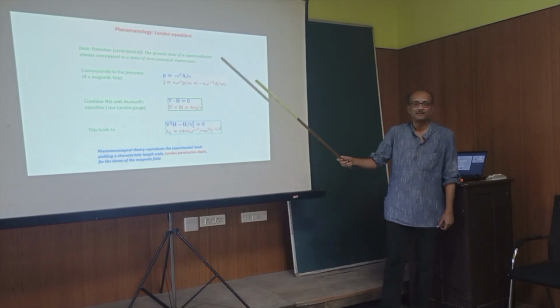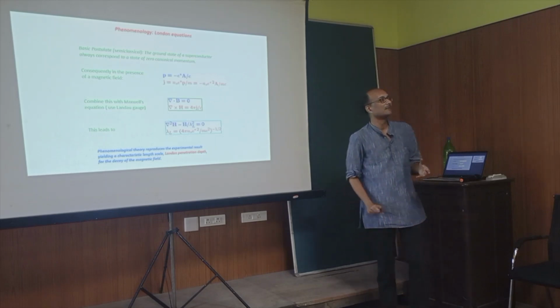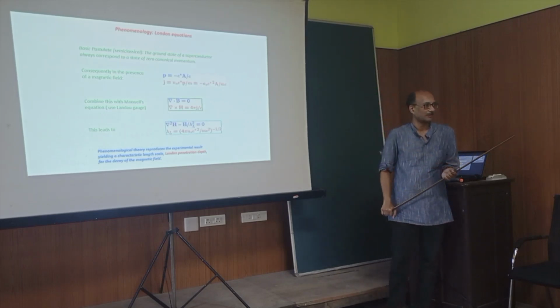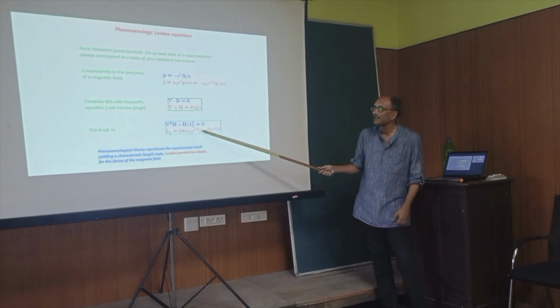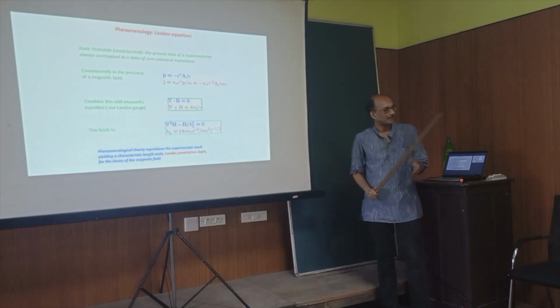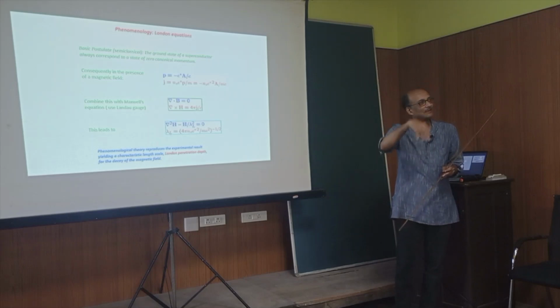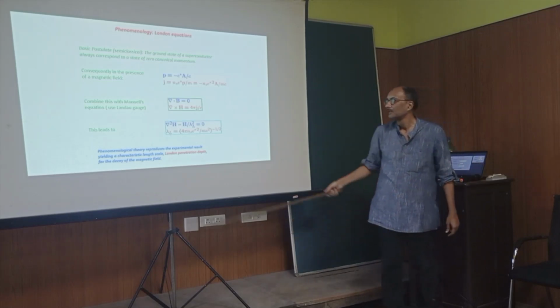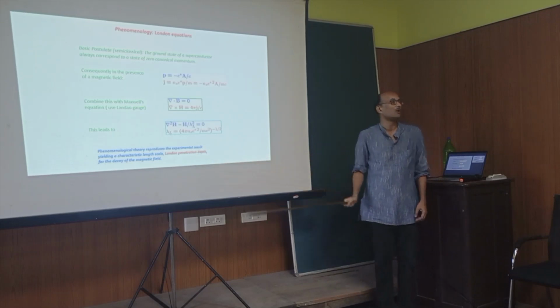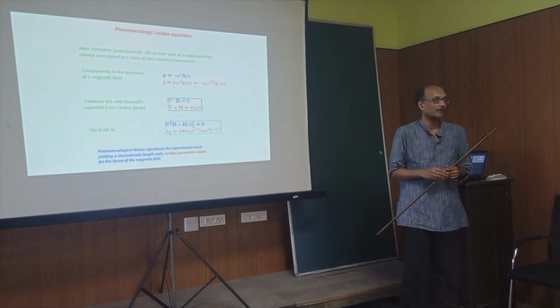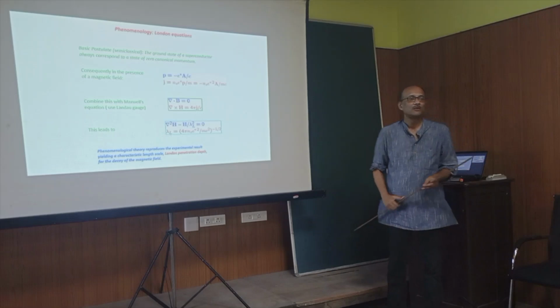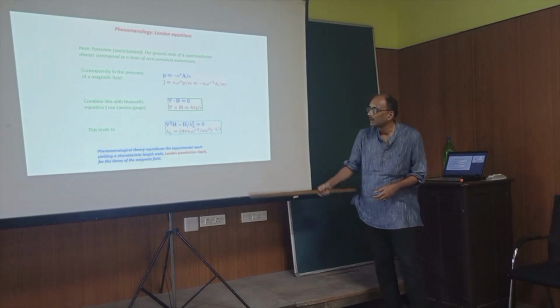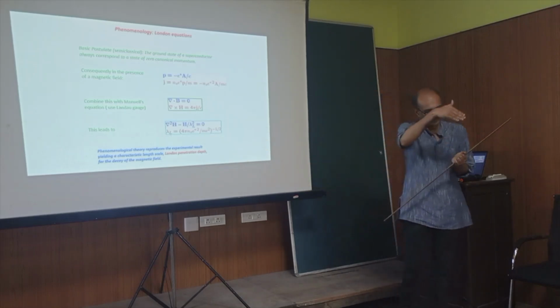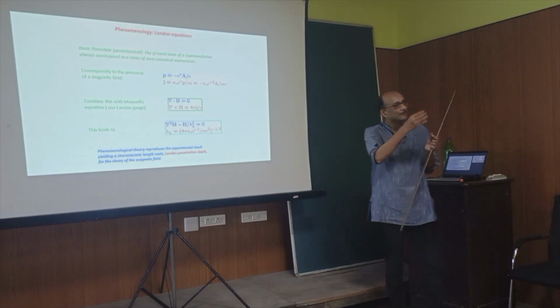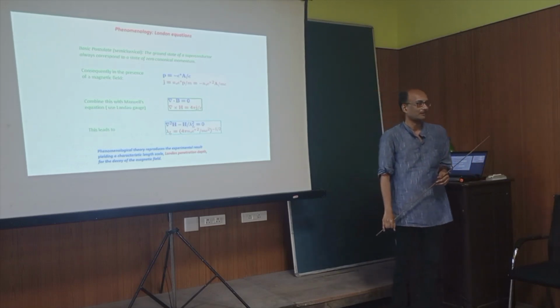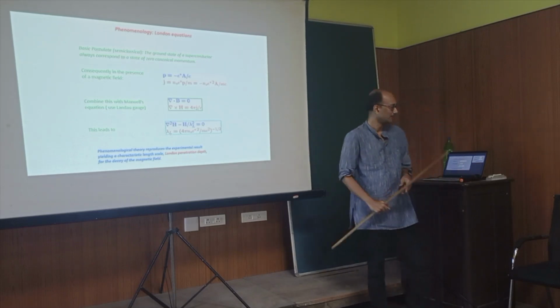And from this simple analysis, not only could London explain why the magnetic field decays inside the superconductor, he could also derive a typical length scale. Okay, that is the depth up to which the field is going to penetrate inside the superconductor. And this length is now known as the London penetration depth. The first phenomenological theory which told one how you could get a length scale which tells you how deep the magnetic field gets inside the superconductor. Okay, so this is the phenomenon.